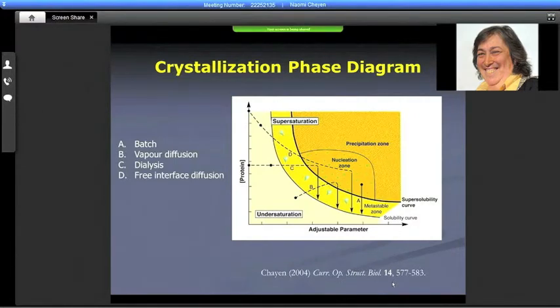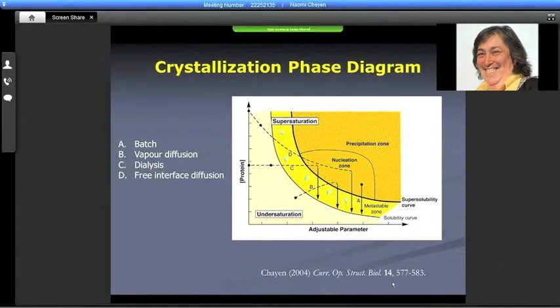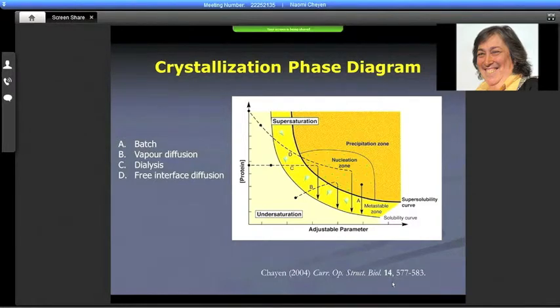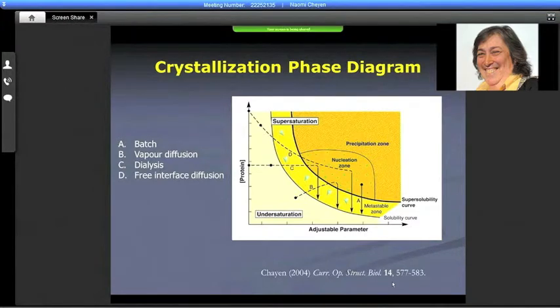To explain what I mean by leading crystal growth, I'd like to show what happens in a crystallization trial. If we take two parameters commonly varied in crystallization experiments — protein concentration and an adjustable parameter such as precipitant concentration, pH, temperature, or additives — one can experimentally obtain a 2D phase diagram showing schematically what happens in a crystallization experiment. We see four scenarios: one where nothing happens at all, the undersaturated area where the protein is in solution and doesn't want to budge; a precipitation zone where the protein just precipitates; and then the two crucial zones, the nucleation zone and the metastable zone.